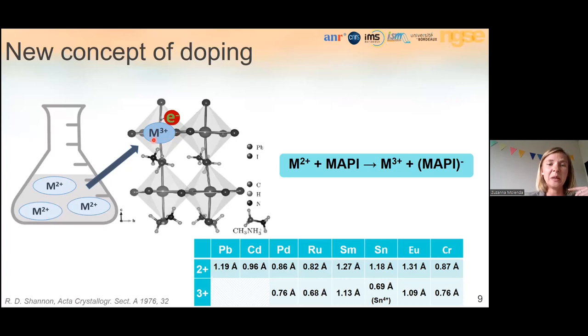The phase separation probably explains the decrease of conductivity at the highest doping concentrations. Zooming into the principal peak for samples showing increased conductivity, we can see the peak shifted slightly toward lower angles, indicating lattice expansion upon doping. This suggests the dopant introduced into the lattice is in the 2+ valency causing lattice expansion, and after crystallization it oxidizes to 3+.